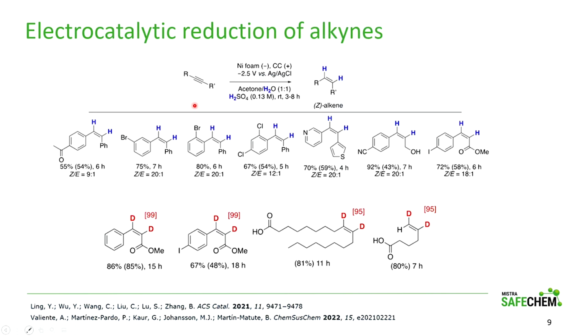So we started investigating this reaction, and this is some of the scope that we achieved, going from triple bonds to double bonds selectively. This is some of the scope, and what we can see here is that the yields are very good. The reaction also tolerates many functional groups, and also what is good is that it tolerates some functional groups that are not compatible with the traditional palladium catalyst.